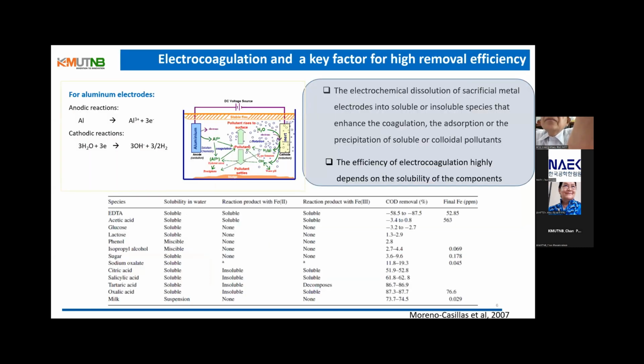For electrocoagulation, it has been demonstrated in the past few years to be an effective method for treating POME and other wastewater containing phenolic compounds. For electrocoagulation, electrical current is applied to the anodic electrodes, such as aluminum or iron or their alloys. The anodes are oxidized to release free metallic ions, which then combine with the hydroxyl ions generated at the cathodes to form metal hydroxides, polyhydroxides, and polyhydroxyl metallic compounds.